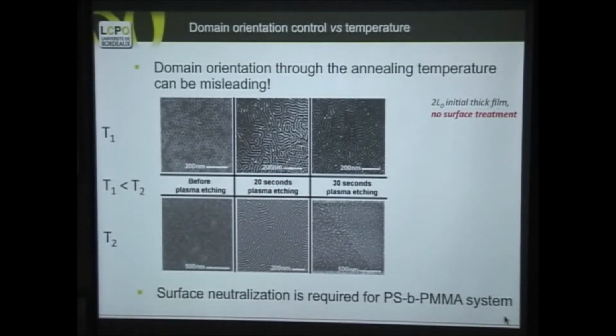First, when we started, a long time ago, 30 years ago, with these polymers, we put them in a thin film configuration and spin cast them at 1 temperature, and this is a cylindrical structure where the cylinders are ordered in a 2-dimensional hexagonal lattice. Here you can imagine, eventually you can think, this is the surface, and the cylinders are perpendicular to the board.